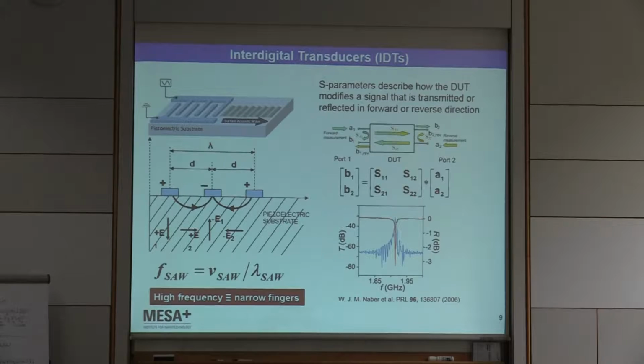The idea is that you apply an alternating RF electric field to these two finger combs, and by alternating, you create an alternating field spatially, but also, if you apply an AC signal, in time, and thereby you periodically induce strain and can produce a traveling wave out of the IDT, in principle also on the other side.